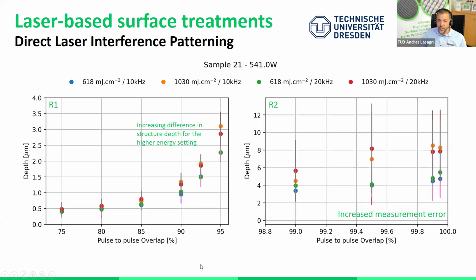Just a little more information. Now we are looking here on the left side, regime 1, where we have very perfect periodic structures. We can not just see the depth information, but also how is the variability of the structure depth in the surface. And we see that here the error bars, this is important for us, are quite small. This is also talking about high quality structures. And in the regime 2 with very high overlaps, the error bars are huge. Of course, we are destroying the material a lot. So this variability is then very evident.